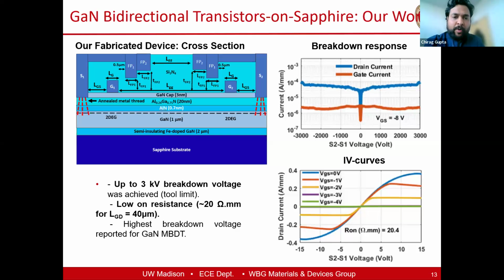0.75 megavolt per centimeter, around that number. So this is something that we would expect. If the field plate design is decent, we can get close to 1 megavolt per centimeter from GaN lateral devices. So currently we are working on pushing this even higher, and what we are trying to do is to see what is the field that we can get out of these devices.